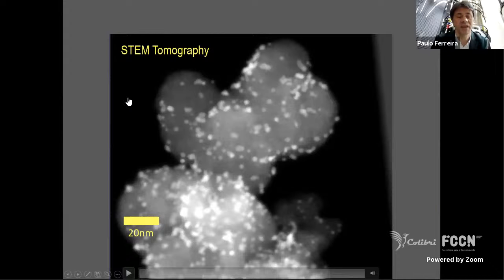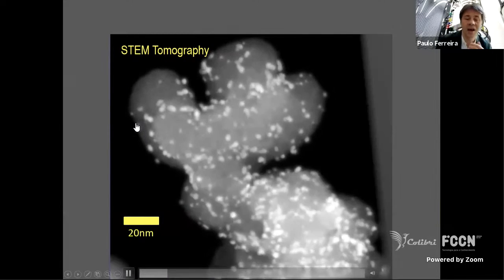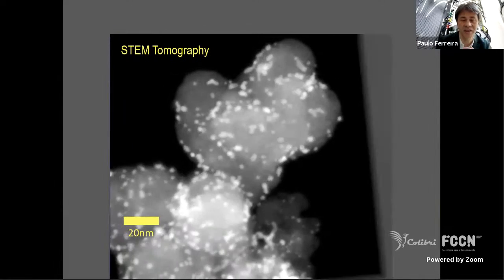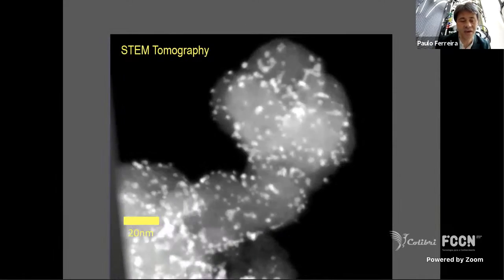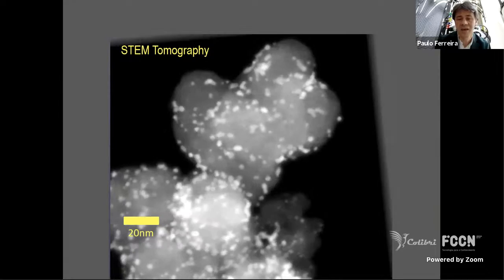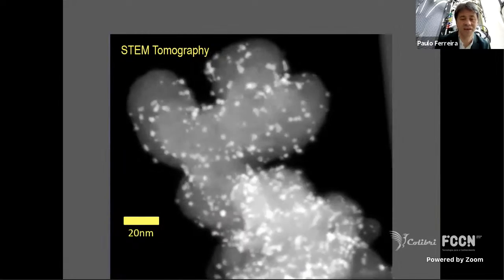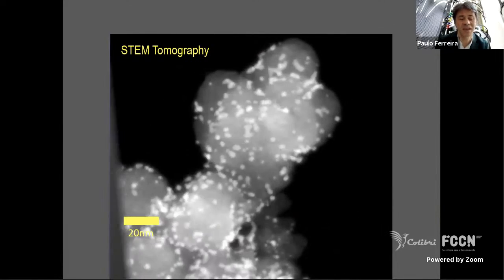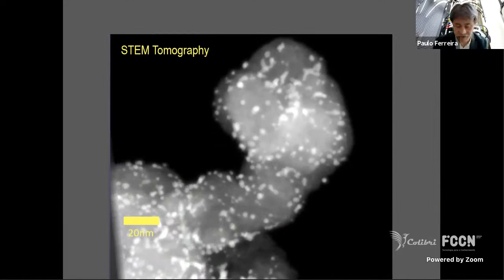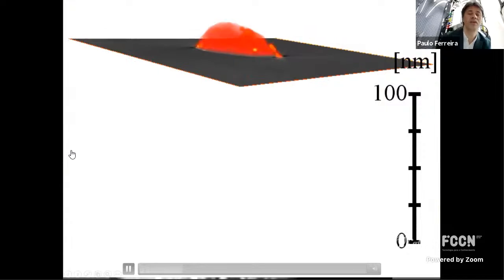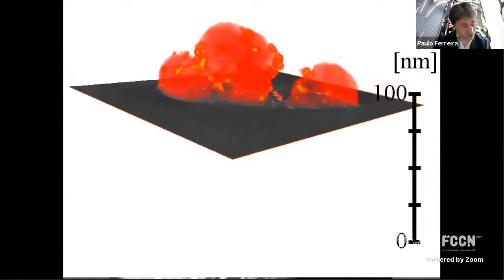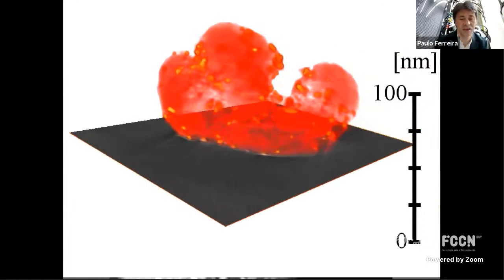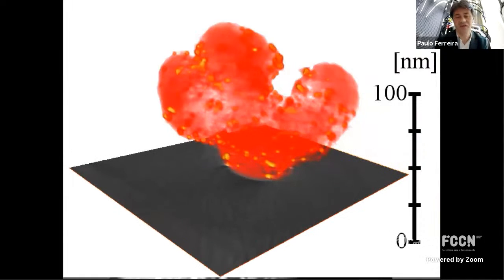More recently, we have been using tomography. So you get a much better feeling, a 3D perspective of these particles within the carbon. You get a much better understanding of how these things behave and where the particles are, and they are misleading many times if you look just at 2D projections. And here's an example of, again, we do these reconstructions in 3D, so then we can just rotate and fully understand what these things are.